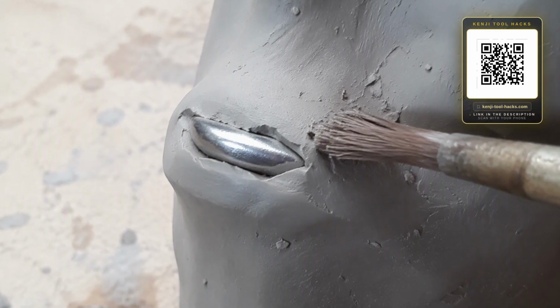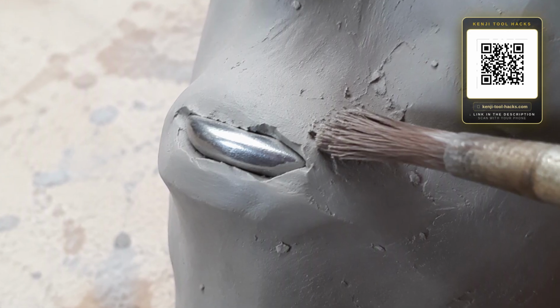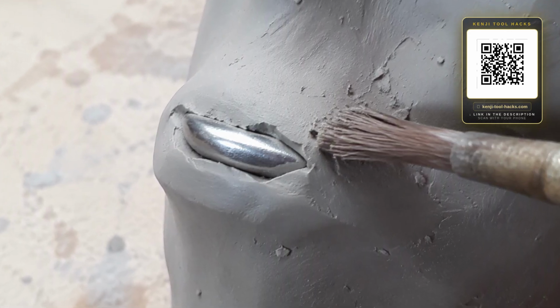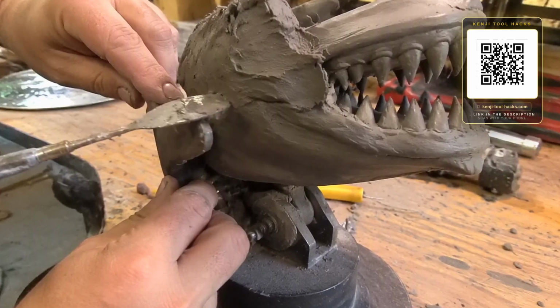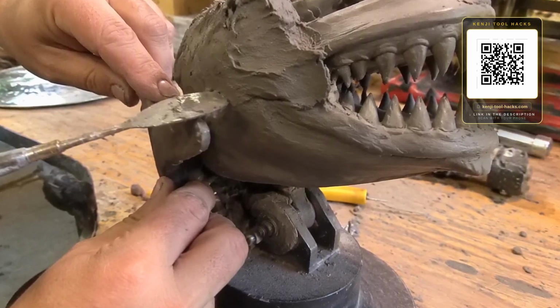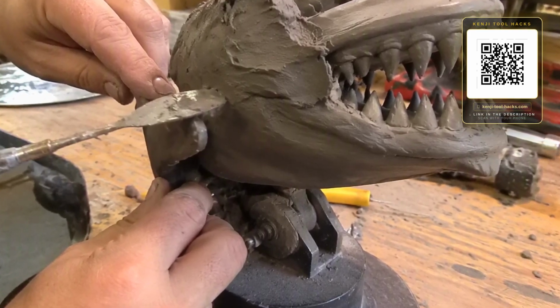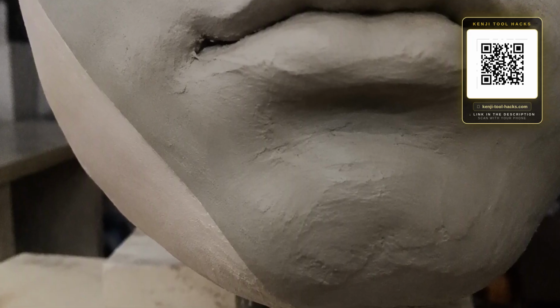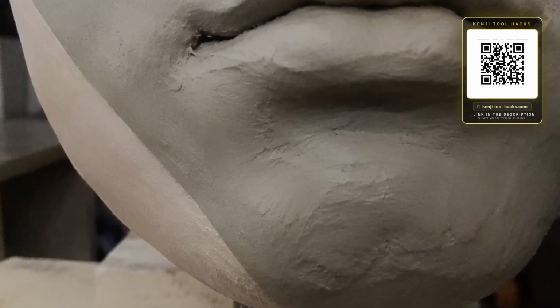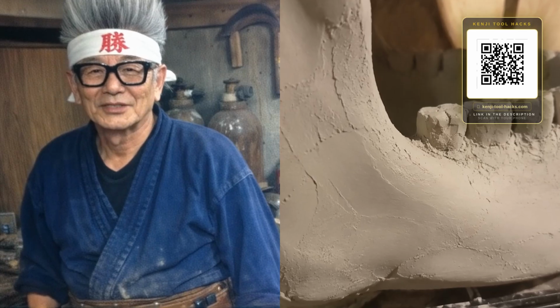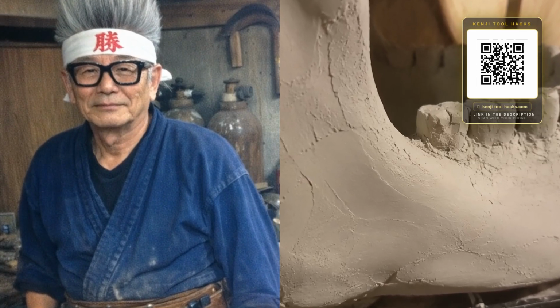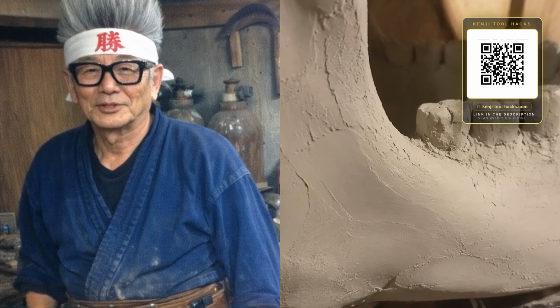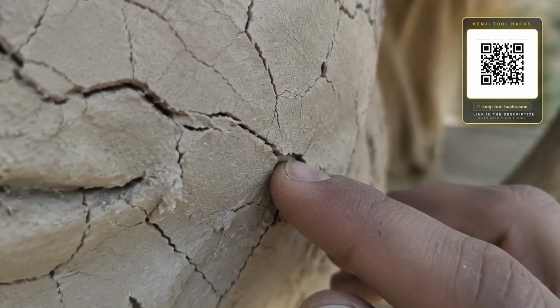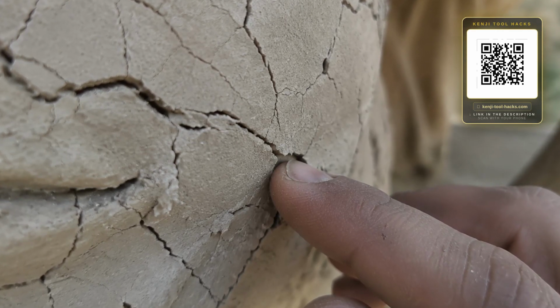Paint the clay onto the jaw, and here is the crucial part. Leave the last 1/16 of an inch right at the cutting edge completely bare, clean steel showing. Then build the clay up thick, 1/8 of an inch or more, over the body of the jaw behind the edge and around the pivot area. You want a clean line between bare edge and thick body, because that line is where your hardness will change. Let the clay dry completely, slowly, until it stops looking dark and wet. If you rush it and it cracks off, you start over.